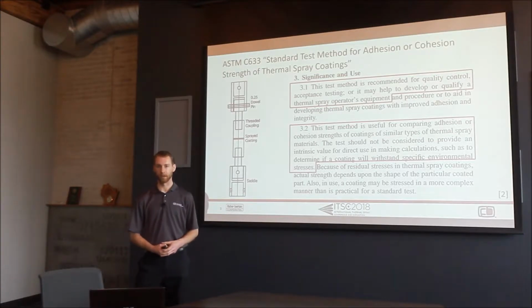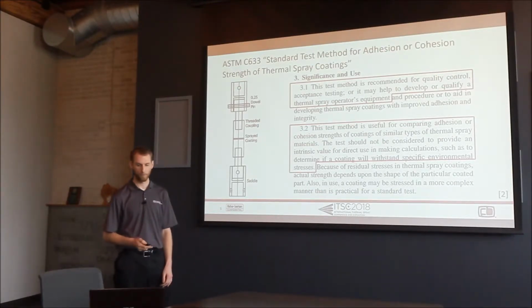And we've seen that through our experience with the 4-point bend method and some other data that we've seen: the limits of C633 are not representative of what you can actually achieve with a thermal spray coating in actual service. So that's the key point of why we looked at an alternative test method to C633, to really consider the true engineering criteria and true engineering behavior of these coatings.